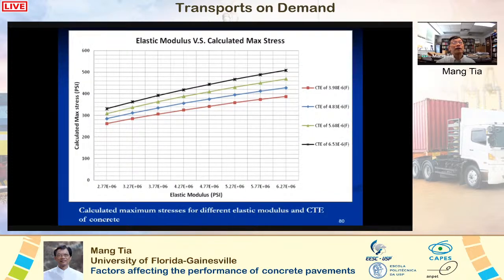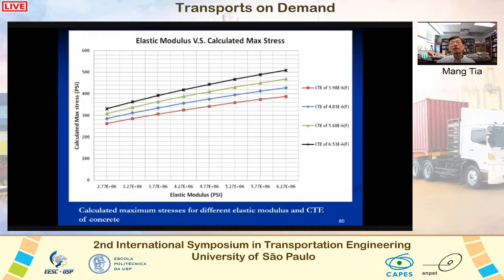These are plots of calculated maximum stress as functions of elastic modulus and coefficient of thermal expansion, the CTE, from a critical stress analysis, and it can be seen that the maximum stress increases as the elastic modulus increases and also as the CTE increases.